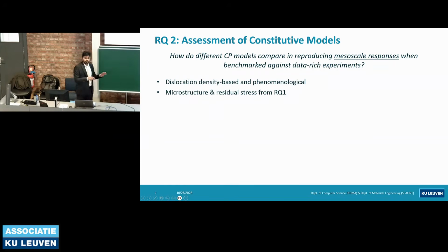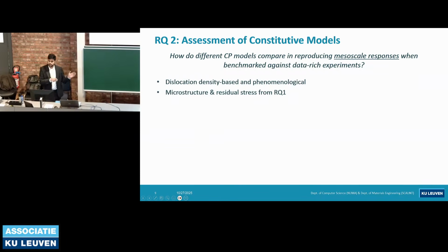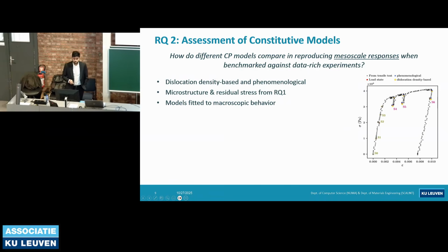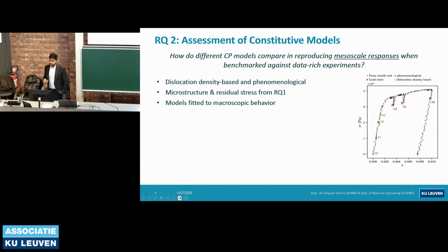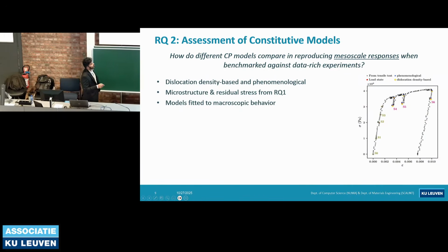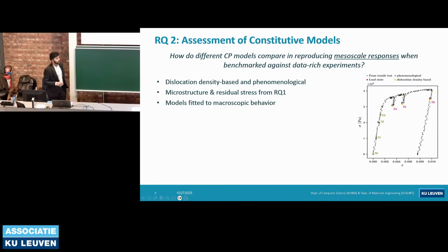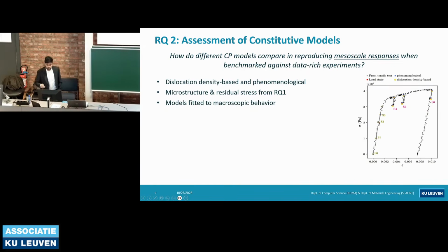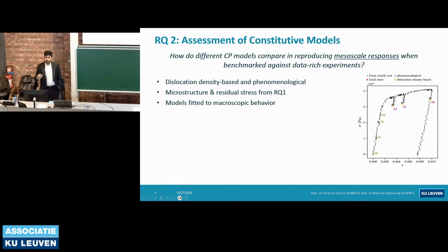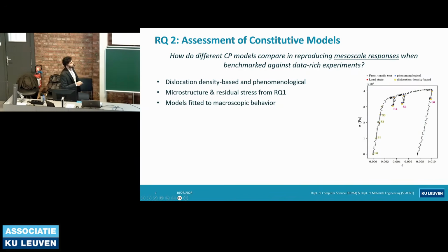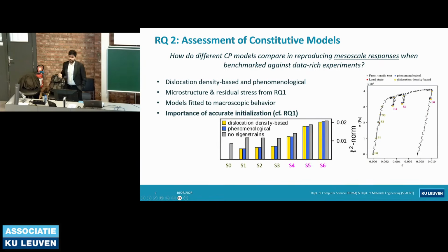So here, the microstructure and the residual stresses from the first research question were taken and used. The models were fitted. Since the comparison or the assessment is done at mesoscale, the macroscopic data was used for fitting these models. As you can see here, the macroscopic experimental data is represented by black markers, and the two models, blue and yellow, were fitted on the macroscopic level. And then for these load states that you see here from S0 to S6, the mesoscale assessment was performed at these load states. But first, let me again emphasize the importance of having accurate initialization.